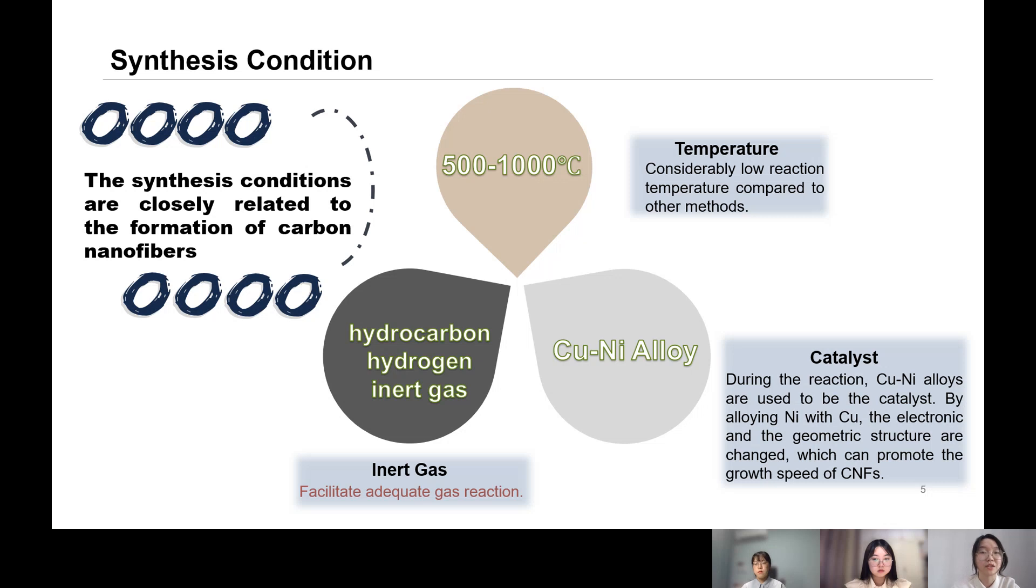These conditions are closely related to the formation of carbon nanofibers. First, the reaction temperature is considerably low compared to other methods. With this temperature, the hydrocarbon can be adsorbed by the upper surface of the catalyst and then decompose to carbon atoms. Then these carbon atoms can diffuse into the catalyst particles, and then the carbon nanofibers can be formed.